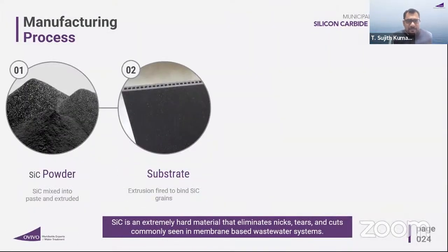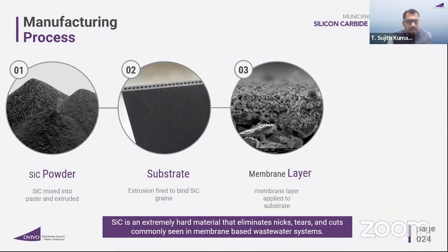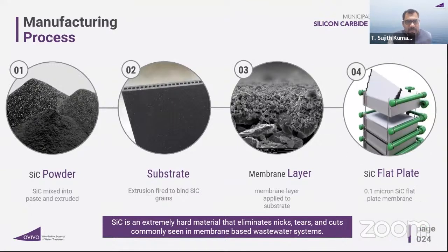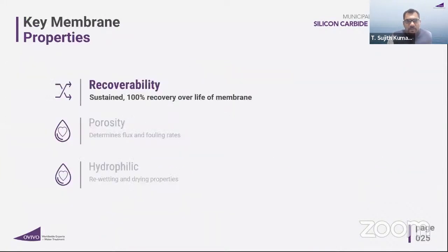Since these are all made out of inert material, it's just a manufacturing process. We have this SiC silicon carbide powder, which is extruded to a paste. We expose it to the sintering process at 2200 degrees temperature. We apply the membrane layer, and the membrane module is formed. It's the Ovivo silicon carbide membrane module.